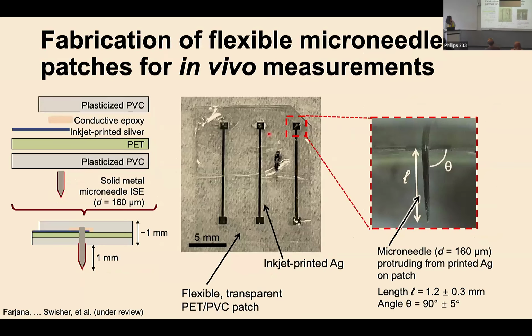We took these needles, and now we're in the process of building this into a flexible multi-needle array, where you can see this is a picture of the needle protruding out of a substrate. Then we have these individually printed traces so that we can access these microneedles individually. We could functionalize one to be the reference electrode, one to be sensitive to calcium or potassium, another for pH. In doing so, we could measure a host of different relevant ions with a single patch.